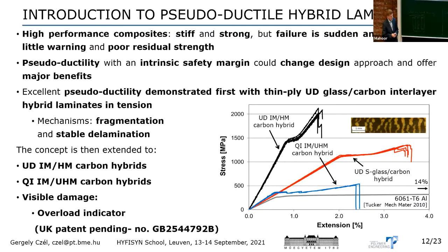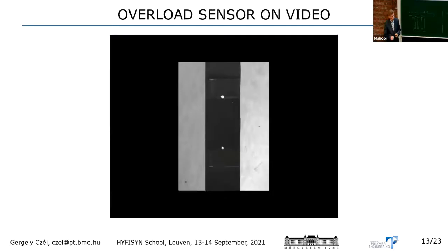Yes, and as we have seen during the video, or we can see on this little picture, if we put the glass epoxy plies towards the outside of the composite, the hybrid, we can actually detect the damage occurring inside the laminate by our naked eyes. It can be either multiple fractures and local delamination, or a single fracture and full delamination. Doesn't matter what the damage mode is, we can see. And this is a very straightforward visual confirmation of what is happening. If we would have a black laminate which disappears from the grips, that's something quite hard to interpret. But what we have is something else.